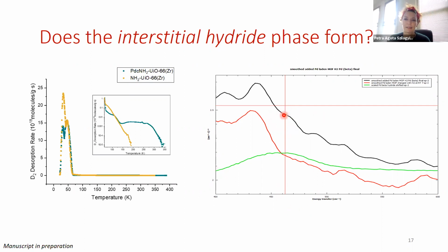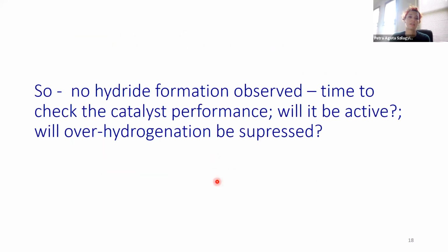And in the case of this simulated spectrum, indeed, there is a bump. So we should be able to see that. However, this is absent in the experimental spectrum. So this also confirms that we don't observe any interstitial hydride formation. So of course, that was the groundwork.